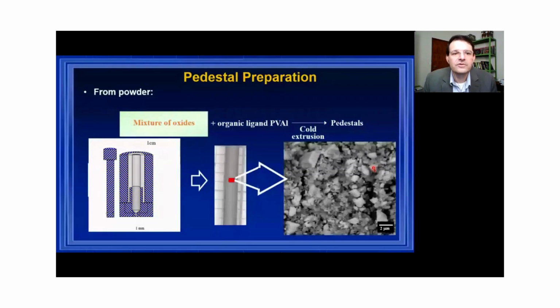You can use just a mixture of oxides with an organic ligand, such as polyvinyl alcohol. So you can create a small pedestal just with a mixture of the powders in the stoichiometry that you would like to have, okay? In this way, in one process, you can liberate the organic, pre-react your material, melt it, and crystal grow it, okay?